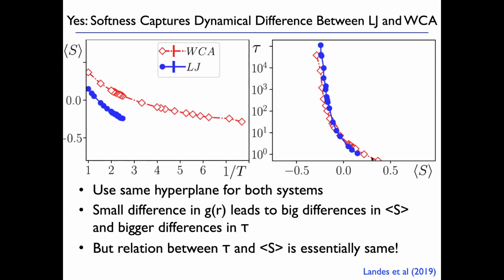So yes, that small difference in the pair correlation function actually leads to a big difference in the average softness, and that leads to even bigger differences in the relaxation time. But the relaxation time as a function of the average softness is the same, or nearly the same, for the two systems.